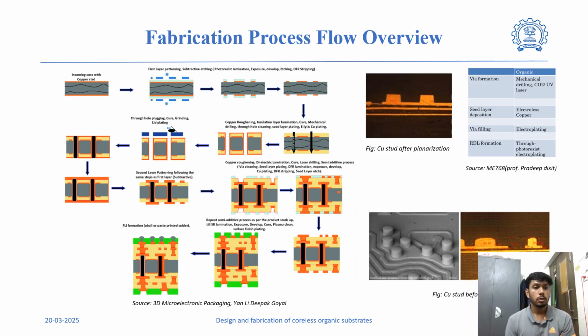The proper insulation between the layers is important to control the leakage and avoid any short circuit. It can be done by introducing the dielectric lamination and build-up layer formation. The dielectric laminations are the thin dielectric layers such as Ajinomoto build-up film or polyimide, which can be used over the patterned conductor.